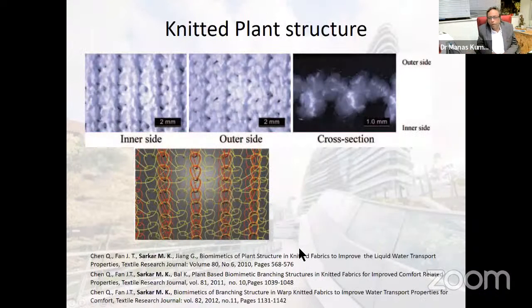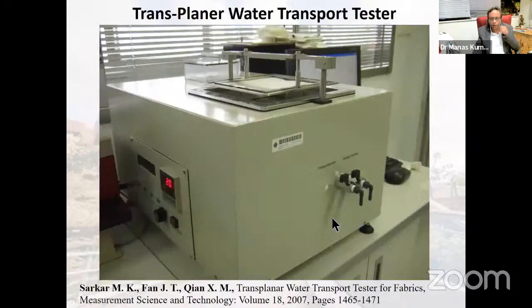In a similar way we developed the knitted fabric structure also. Here you can see that in the outer layer it is more open, and in the inner layer it is grouped together. This is the cross-sectional view: the inner layer is grouped together, and it opens up more in the outer layer. Here you can also see the view of the knitted structure. This way we developed a kind of branching structure inside textile fabrics. I have already put in a lot of references, you may see them if you are more interested.